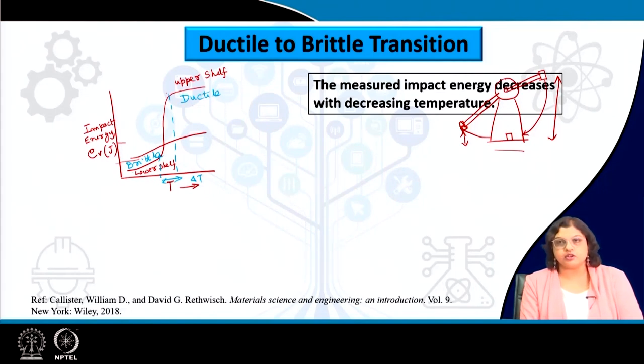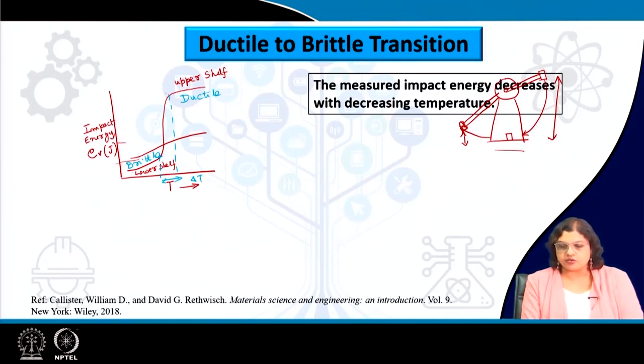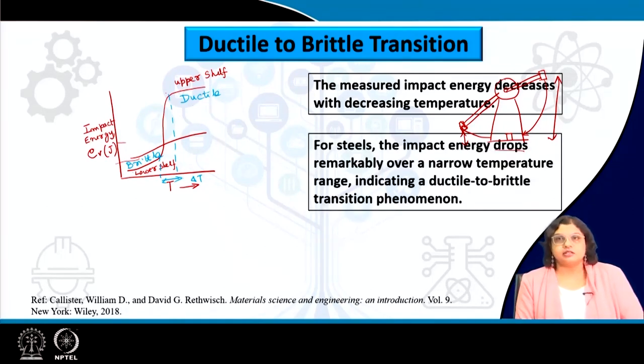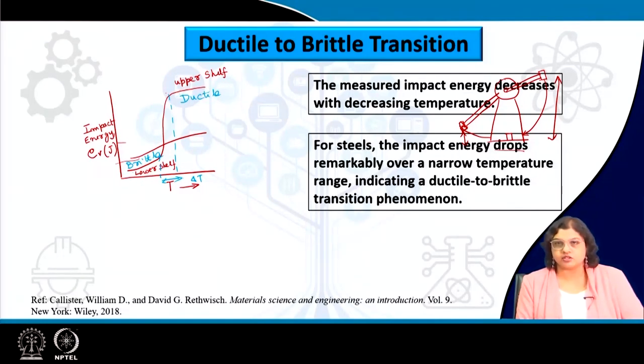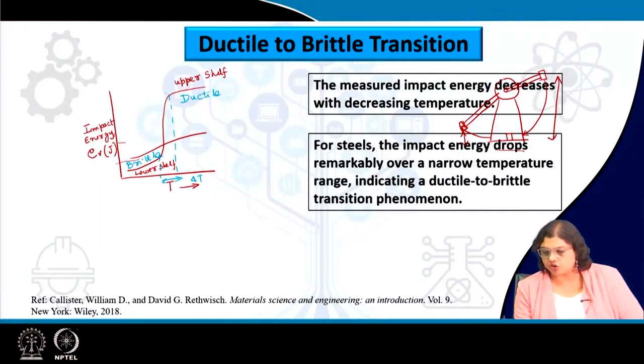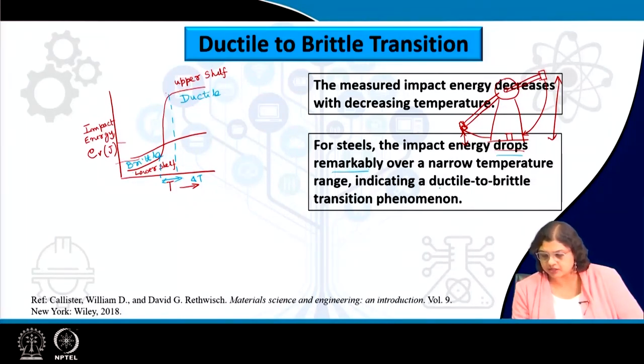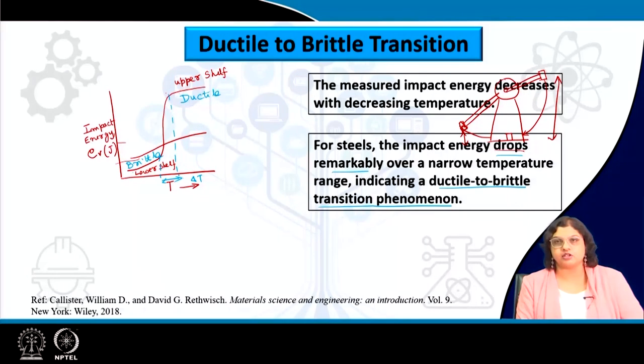This is essentially figured out from the Charpy impact test. What we are concerned with is the temperature range over which this ductile to brittle transition is happening. This change in failure mode is seen for certain materials, particularly depending on their crystal structure — we see this for steels, where the impact energy drops remarkably over a narrow temperature range. This is known as the ductile to brittle transition temperature, or DBTT.